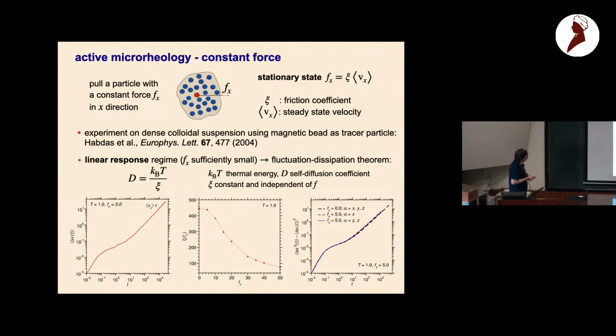Via this steady state velocity, we can then determine the friction coefficient, and this is now shown here as a function of force. So with this force, this is the example F equal 5, we are close to the linear response regime. This point is computed from the self-diffusion coefficient. And then we have this decrease, which marks, as a function of force, the nonlinear response.